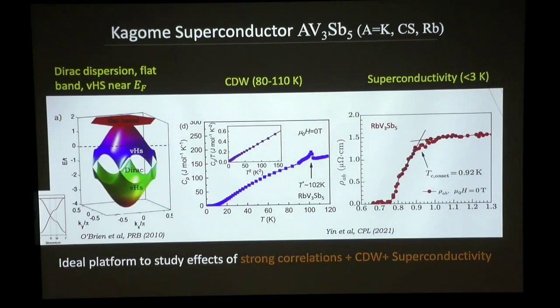So the reason these Kagome compounds are interesting is that a lot of them have both Dirac dispersion, 3D Dirac dispersion, as well as flat bands. In this particular Kagome compound, the flat band lives very high above the Fermi energy. The interesting thing about flat bands is if you can bring the flat band close to the Fermi energy, you can have very strong correlations. That doesn't happen in this compound, but instead you do have high density of states due to these so-called Van Hove singularities where the band bends over like this. And that high density of states is responsible for a lot of interesting physics in these compounds.